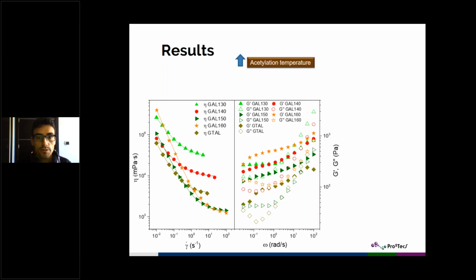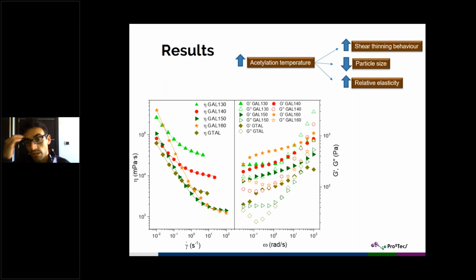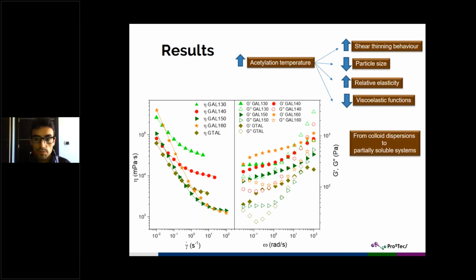So just as a summary, just an increase in the acetylation temperature increases the shear thinning behavior, reduces the particle size, increases the relative elasticity of the sample, and reduces generally, at least, the viscoelastic function. So we pass from colloid dispersions that are not so well structured to partially soluble systems that generate a really good system with a very good shear thinning behavior typical of commercial lubricating greases.